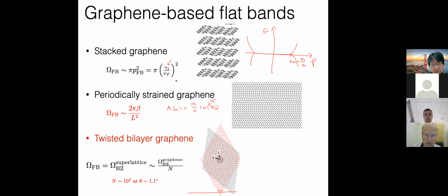I see. Maybe for the other two cases, the physics is basically the same, right? In the case of periodically strained graphene, you assume the band comes from the superlattice. Yeah, it comes from the superlattice, but slightly differently. In this case, the flat band is a Landau level of this pseudo vector potential, but rather than considering a constant pseudomagnetic field, like people usually do, we actually look at the periodic pseudomagnetic field. In reality, the periodic pseudomagnetic field is much easier to realize than a constant one, because a constant one does not work. You have to infinitely extend your system. It only works for some finite region. But the Landau level picture is still useful to think about.